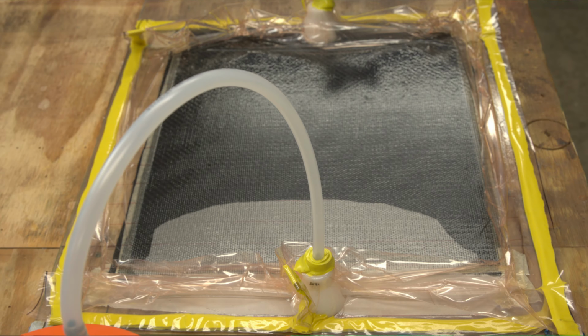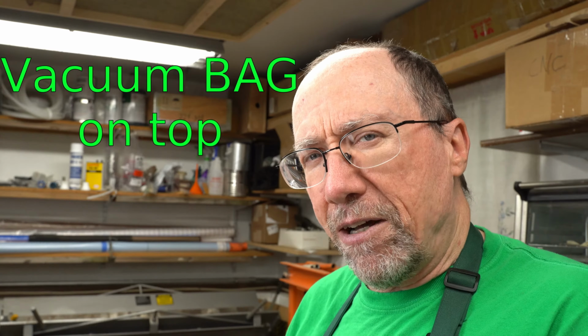And I intentionally removed all wrinkles from the vacuum bag when I put it in, just so I could find out what the screen by itself would do. Well, obviously it didn't work. I got roughly the same result as the previous two tests. And I thought about it, and I think what was happening is that the very small crimps in the screen were being plugged up on the vacuum side on top and on the peel ply from underneath. So I needed just a little bit larger crimps that wouldn't get plugged up.